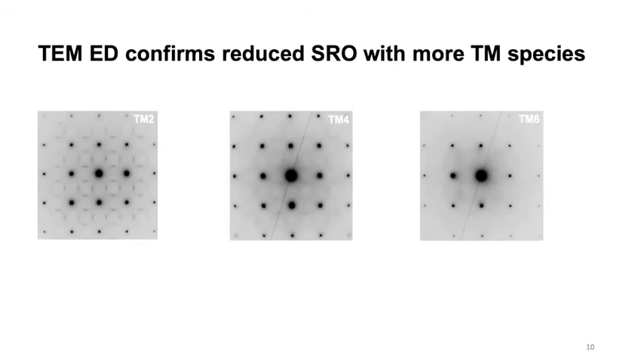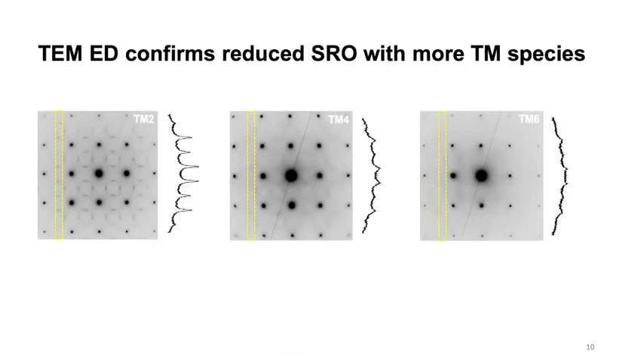And we can see when we move from TM2 to TM4 to TM6, the intensity of the diffuse pattern significantly reduces. In other words, the short-range order in the material can be reduced when we incorporate more transition metal species. A quantitative analysis integrating the short-range order intensities also clearly shows that the short-range order feature is significantly reduced from TM2 all the way to TM6 when we have more transition metal species.